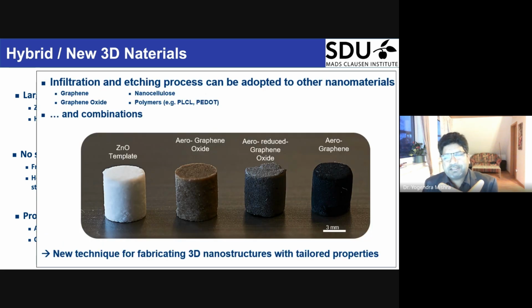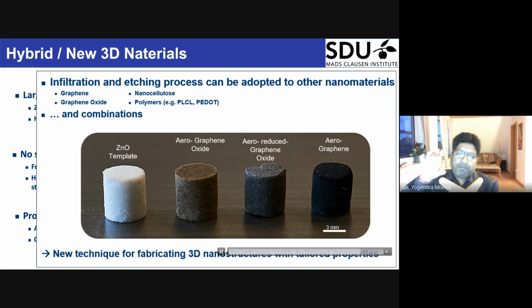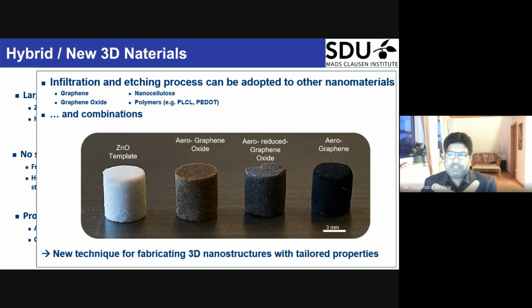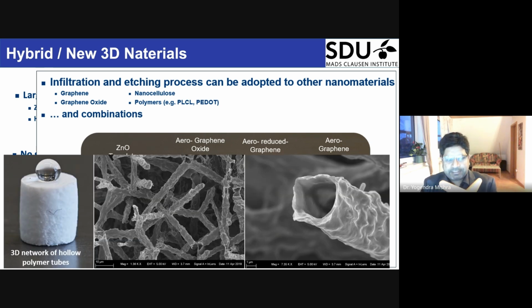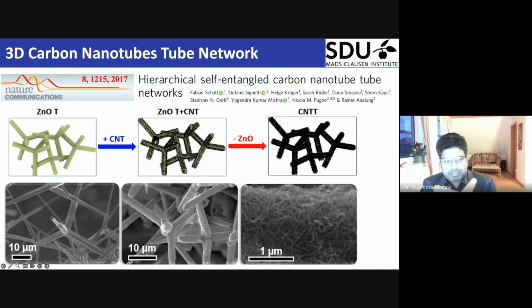But if one requires a new material, then by chemistry we could remove the underneath backbone, and then we could get a new material exactly in the same template form, 3D network form, with a high degree of porosity, a sponge-like material. And this has been our state of the art in the last 5-10 years. We can create almost every kind of new 3D material by the same process, using these networks as a template. You can see this is a PDMS network, with whatever degree of porosity you can prepare. This is the typical carbon nanotube network we can make in this story.